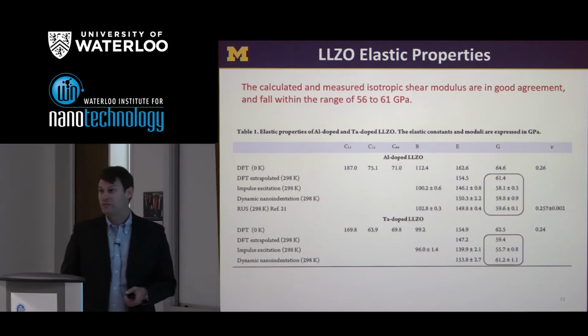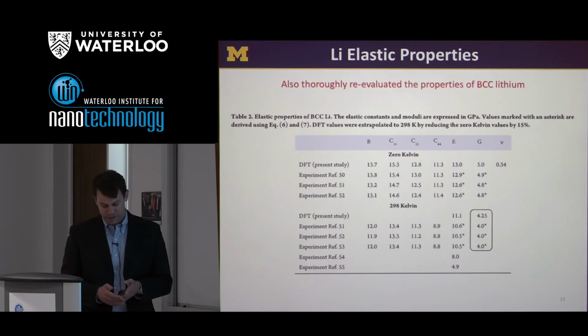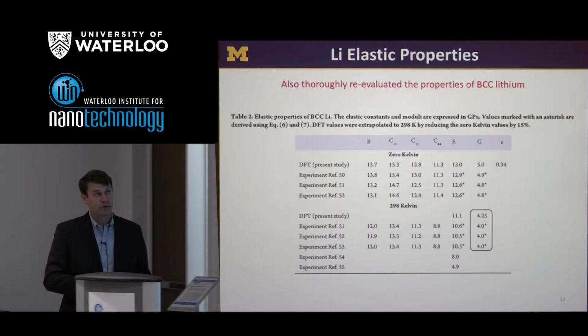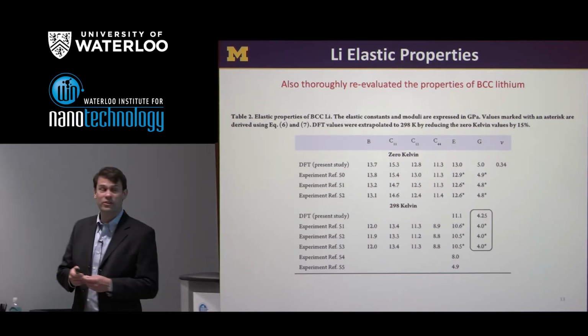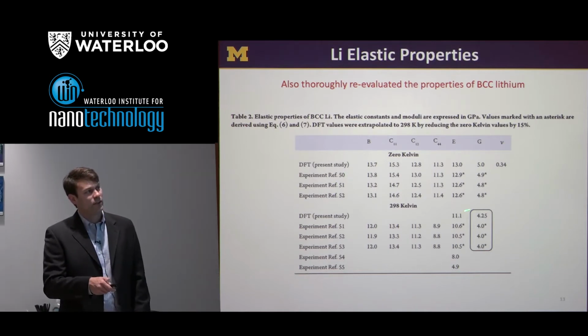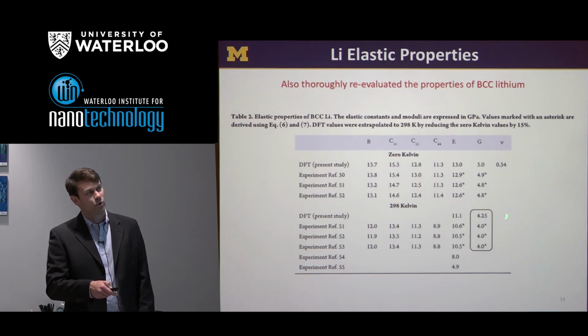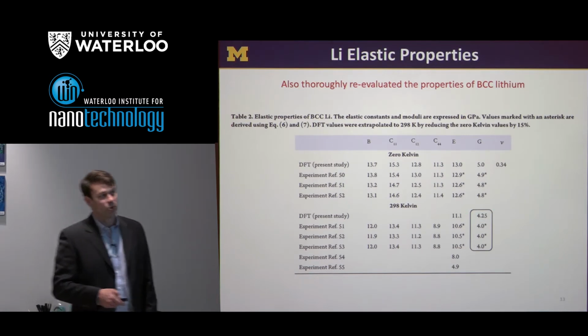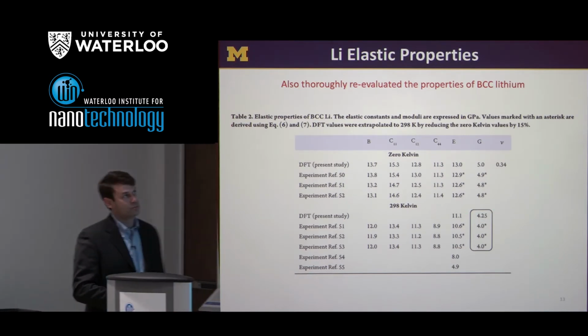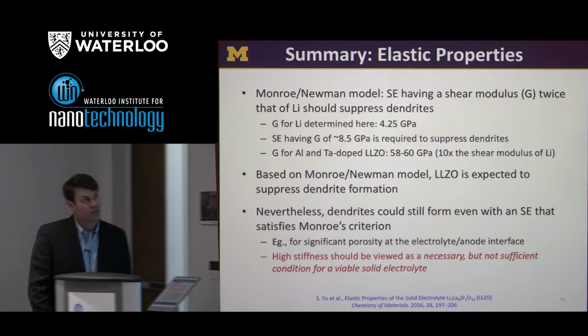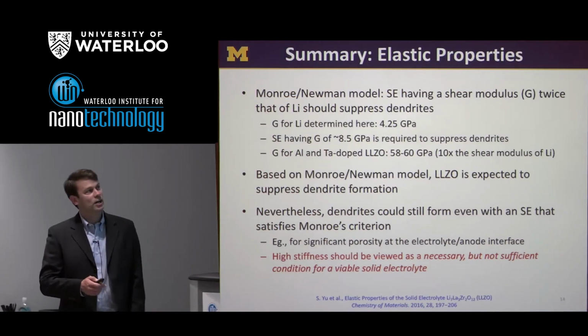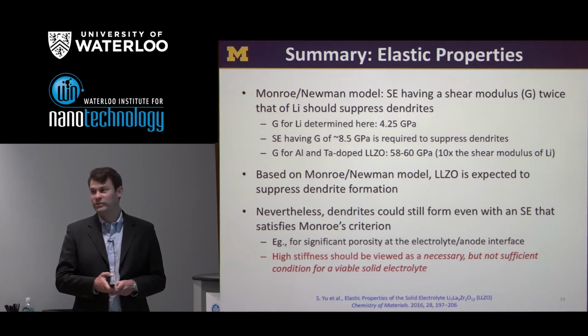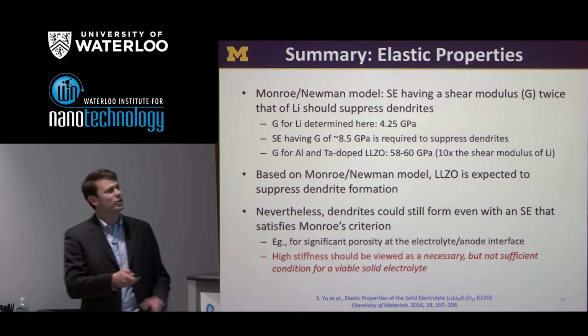This is also a relatively high shear modulus, which gives us some confidence that, at least according to the Monroe-Newman model, we'd have some hope of suppressing dendrites. And of course, we want to compare with the lithium value. So we also reevaluated BCC lithium. And so this is our calculated value of about 4.25 GPa for the shear modulus. That agrees rather well with some older experimental measurements. So as you can see, we are well above this factor of 2 threshold to satisfy the Monroe-Newman criterion.